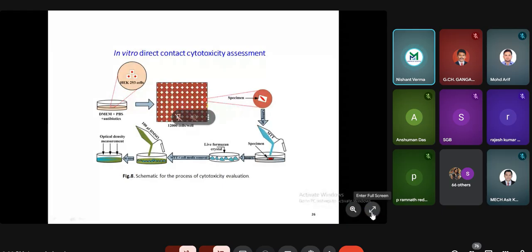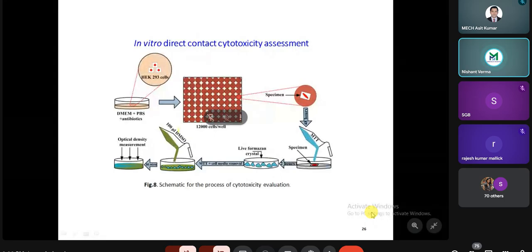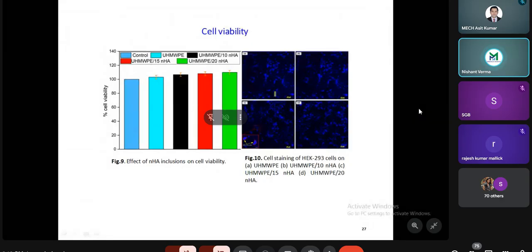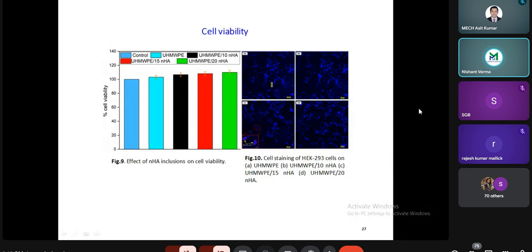We supplemented with the bovine serum, and after that we put in the MTT solution, and this converted into live formazan crystals. And the formazan crystals we dissolved in 100 microliters of DMSO, dimethyl sulfoxide, and after that we did the optical density measurement. The principle is that the higher the optical density value, the higher the cell viability. So we can see the cell viability here in the microscope. All the specimens support cell viability and cell proliferation.